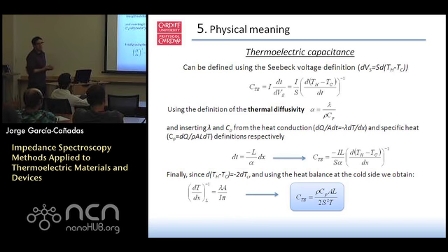We have introduced as well a thermoelectric capacitance. Thermoelectric capacitance can be defined using the Seebeck voltage definition. It is just the variation of charge versus the Seebeck voltage. So current times dt, over the Seebeck voltage. If we introduce the definition, we have this expression. So it relates with the speed of the temperature increase, the reciprocal.